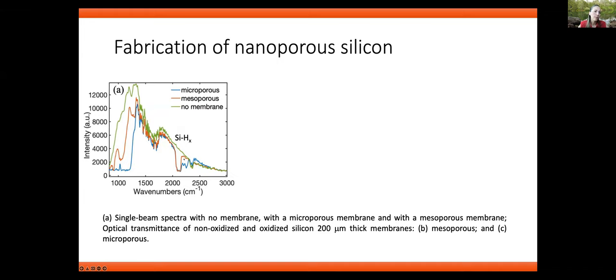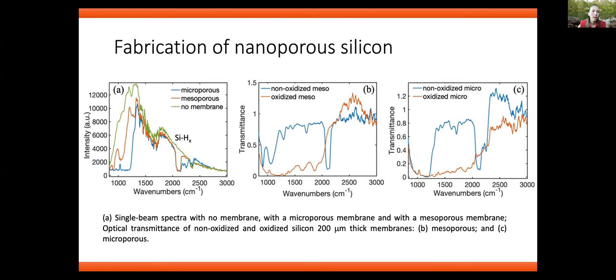We can also see very strong silicon-H bonds. When the samples are freshly etched, we can see this bond, but over time, silicon oxidizes and this will become silica. And then we actually forced our membranes to oxidize. So we put them in the oven at 900 degrees for a few hours, and that transforms all the porous silicon to porous silica. And why we do that is that we know porous silica will be stable, will not change its properties. Whereas if we use porous silicon, over time, it will keep on oxidizing in the air, which is not great for a sensor to change its properties.